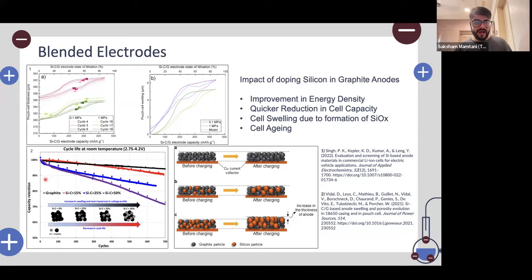If you look at this particular graph on the bottom left of my screen, you can see there are four different discharges. The graph is between the capacity retention and the number of cycles. And these are for four different materials. You have just a plain graphite anode. You have a graphite anode with 15% silicon doped. You have a graphite anode with 25% silicon doped and 50% silicon doped. And you can see as you're increasing the silicon doping, you end up aging the cell quicker compared to a cell which does not have any doped silicon. It has plain graphite. Within 700 cycles, you can see a drop of capacity by around 25%, whereas this is somewhere still close to 95%, this is dropped to almost 70%. So this is a very big drawback, and this is one thing that the R&D industry at the moment is trying to work towards.